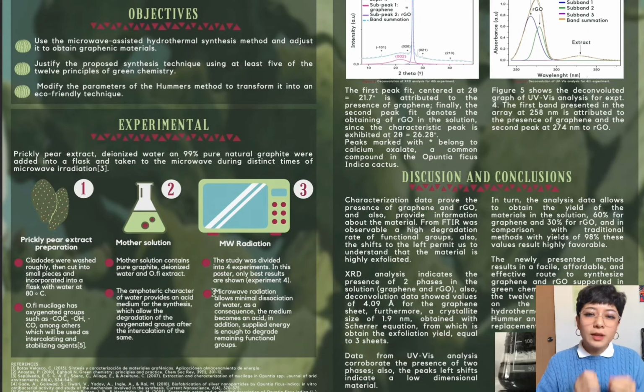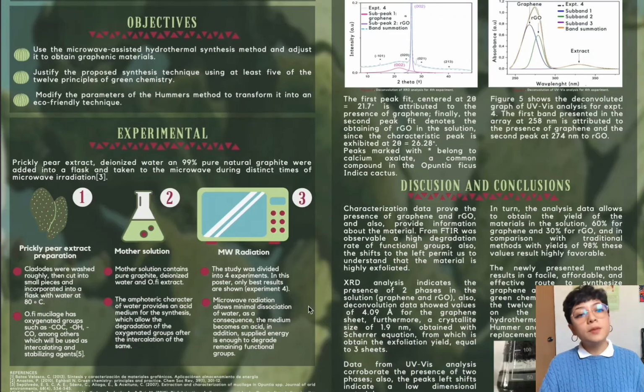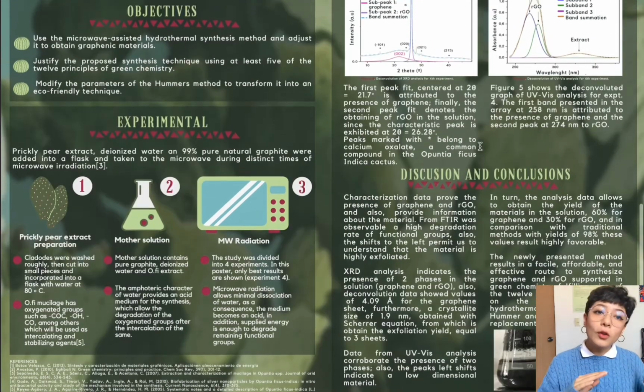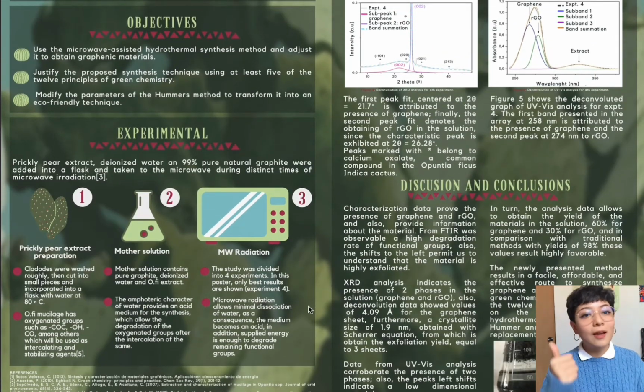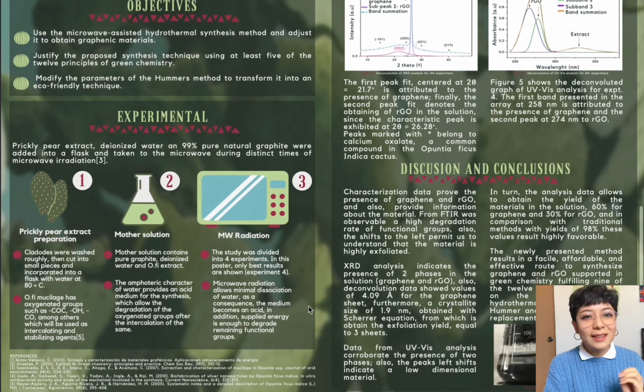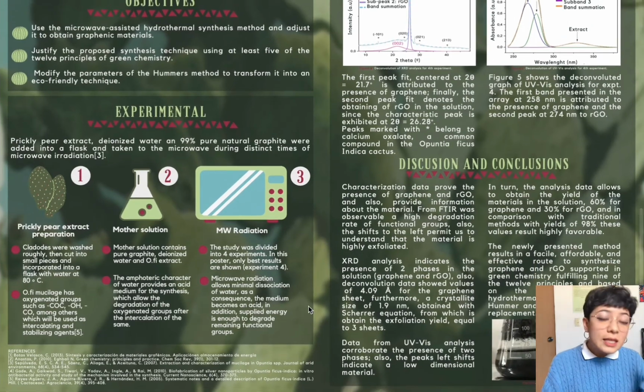Now, microwave radiation allows minimal dissociation of water, so we obtain a hydrogen ion and a hydroxyl group. As a consequence, the medium becomes an acid. In addition, supplied energy is enough to degrade the remaining functional groups. Here, steps 2 and 3 fulfill the other Hummers' method requirement to have a strong acid. This one-step system permits the oxidation of graphite, the intercalation of the oxygenated groups into the structure, their degradation, and isolation of the sheets to obtain graphene and reduced graphene oxide.